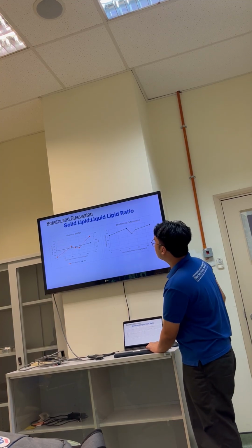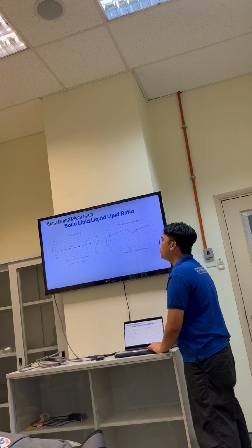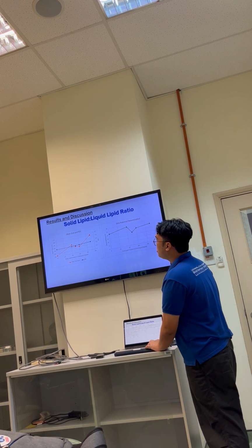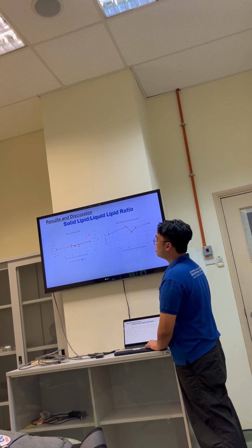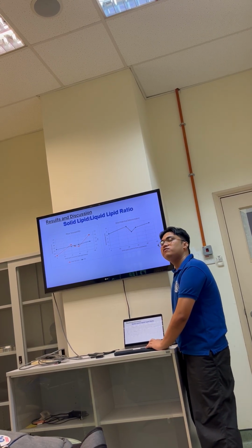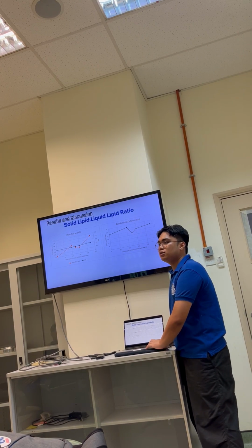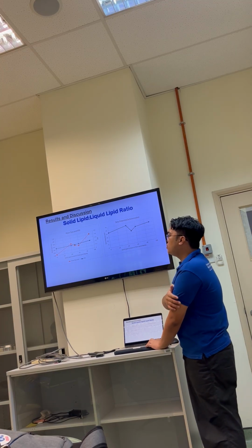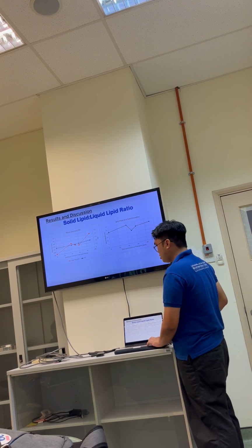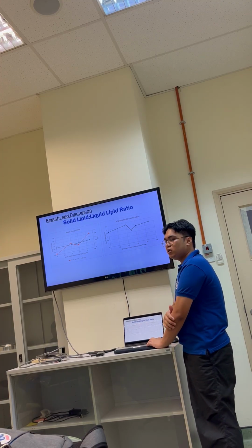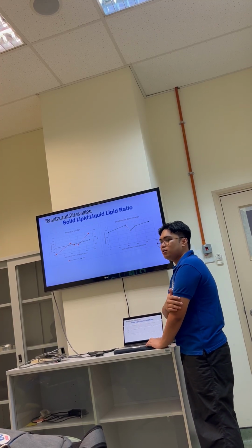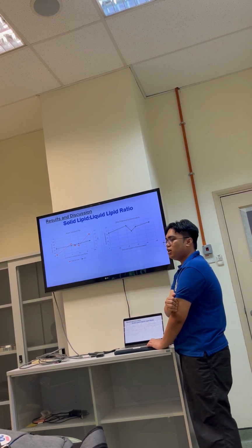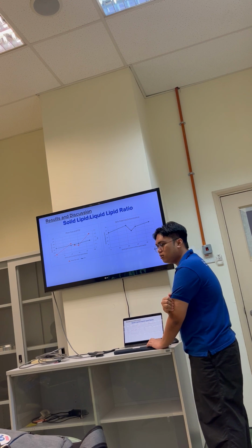As for the solid lipid to liquid lipid ratio at 5% total lipid component, we can see here that it's very clear though that increasing the solid lipid content does also increase the mean size. As I've said earlier again, the viscosity likely plays a huge role in this. So a more viscous melt because of a more viscous solid lipid component, then we can get larger sizes for that. And actually this is the reason why NLCs can be quite tweakable in terms of its size, because of course we can tweak the solid lipid content and total lipid content, which is theoretically and also practically from related papers also very prevalent.